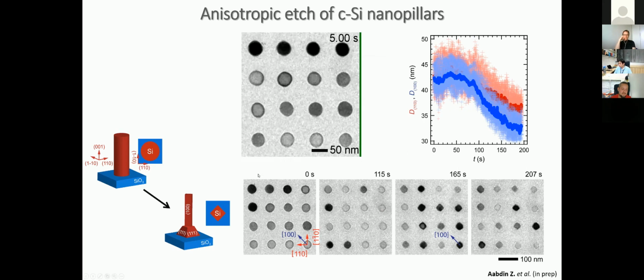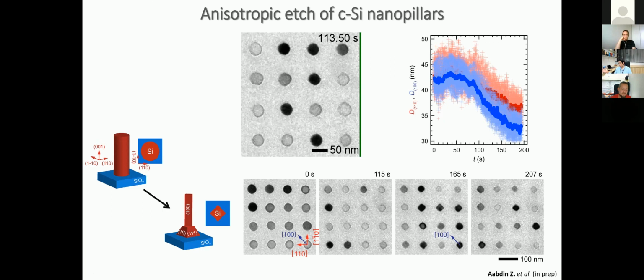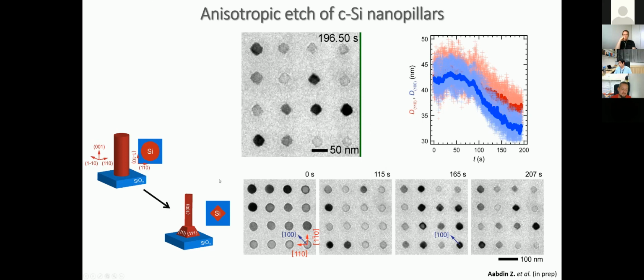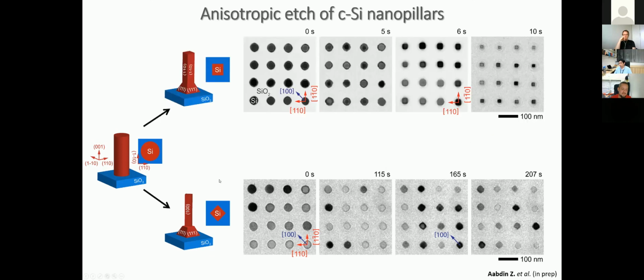Okay, so this is not super surprising. This is what you expect, how a silicon should etch. But as a serendipity, my former postdoc discovered, actually you can control etch directions. If you do a KOH or TMAH etch, your etch directions are dictated, right? So you have fast etch planes, and then you have slow etch planes. But apparently,